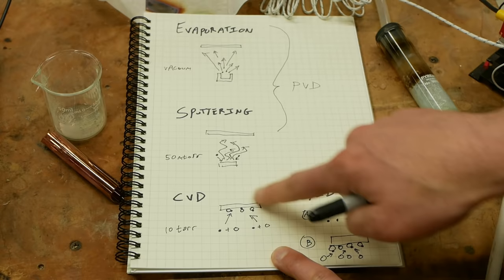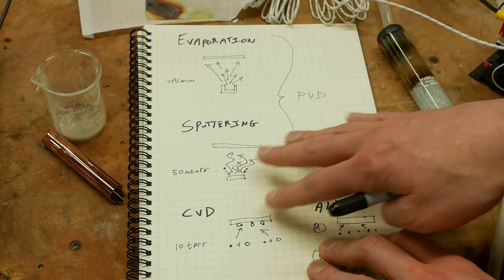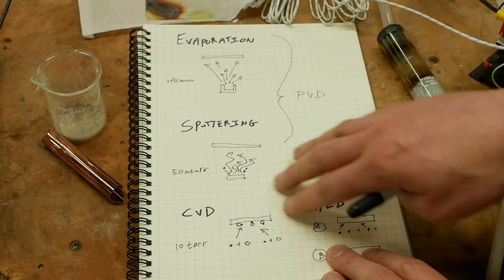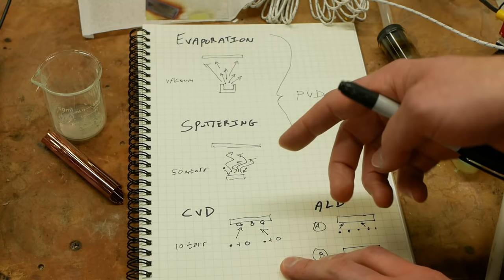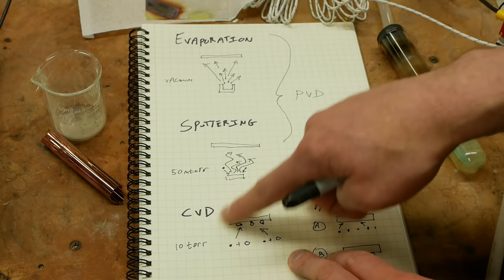The neat thing about this is that since we're at higher pressure again, the uniformity is very high because the gas flows all around it. So if evaporation is super directional, sputtering is pretty directional. CVD is not directional at all because the gas can flow around everything. But there is still some amount of control not happening here. Your substrate might be very slightly hotter in one region or there could be a surface imperfection that causes the reaction to happen faster or slower. So even this is not ultra, ultra uniform.